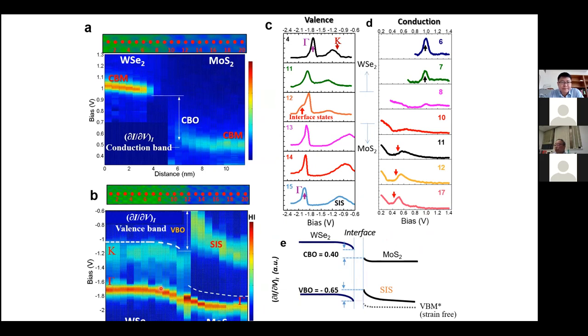And then in the valence band, what I show here is really the WSe2 and MoS2. The bright signal right here is the gamma point. The K point of the WSe2 and the gamma point are about 0.6 eV apart, but for the MoS2, it is only about 0.2. So this would almost imply there should be about a 0.4 eV band offset with the WSe2 above MoS2.